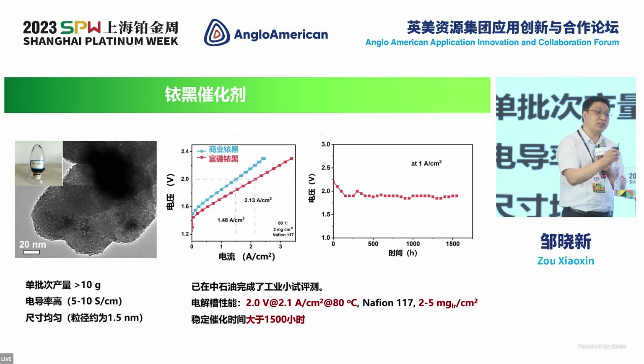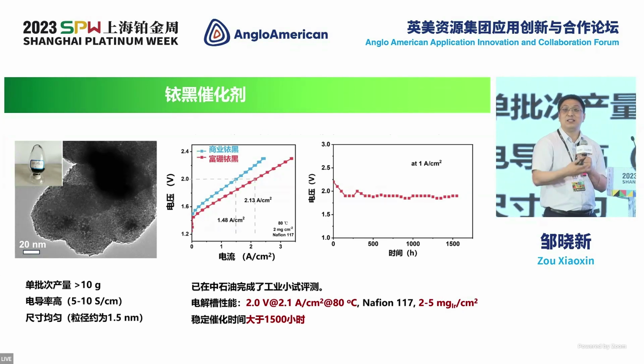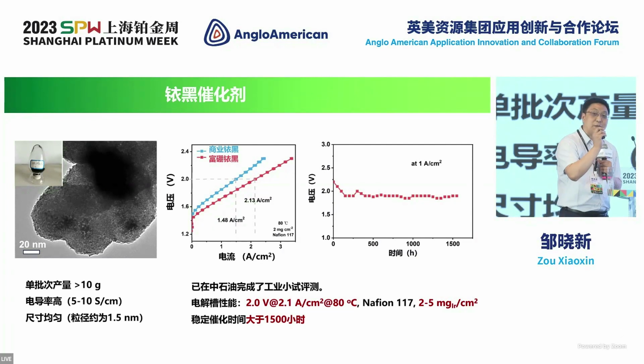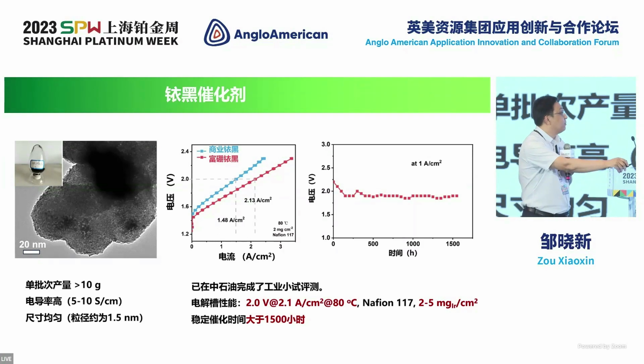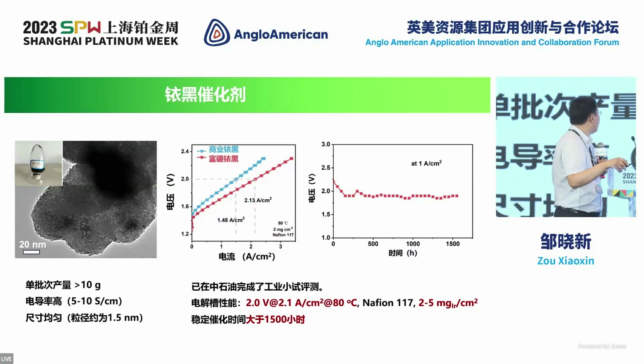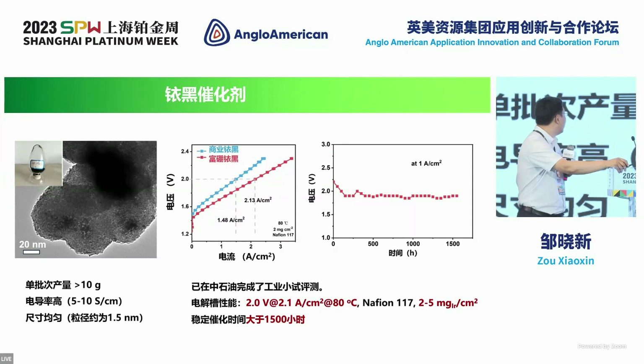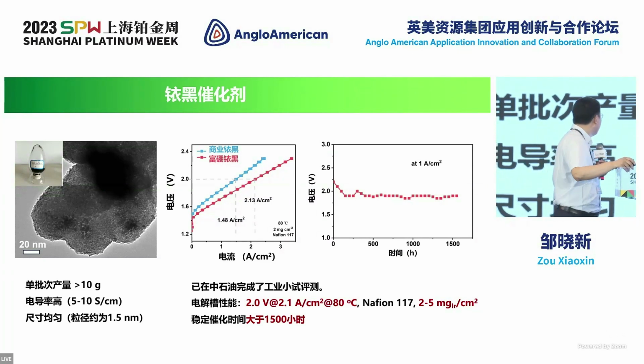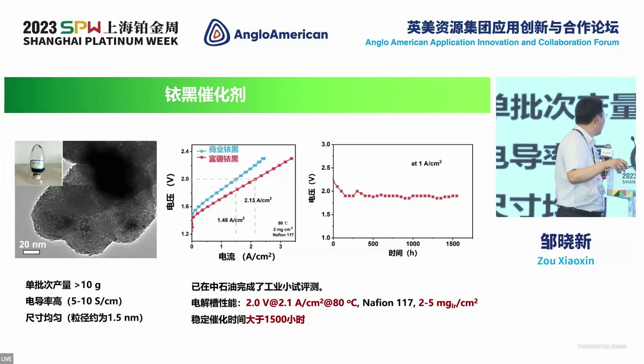This is iridium black. Some iridium black is very electrically conductive and some is not as much. The reason is that, first of all, you need to ensure the dispersion of the iridium nanoparticles, and you also need to make sure the particles are suitable for water electrolysis. In our lab, we can balance these two features. So the conductivity is about 5 to 10 Siemens per centimeter.